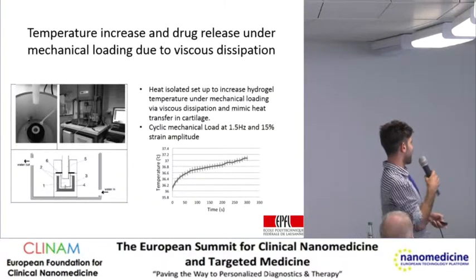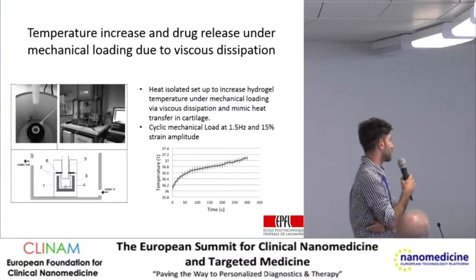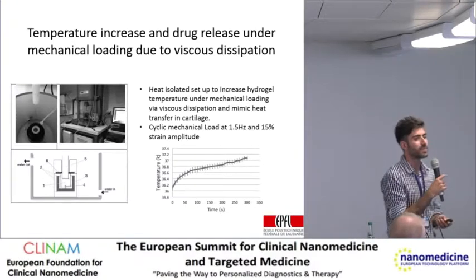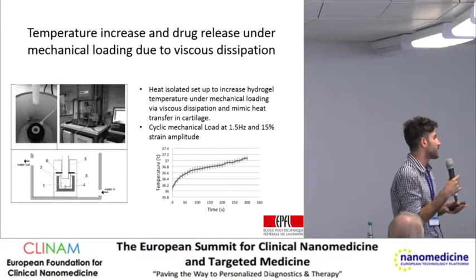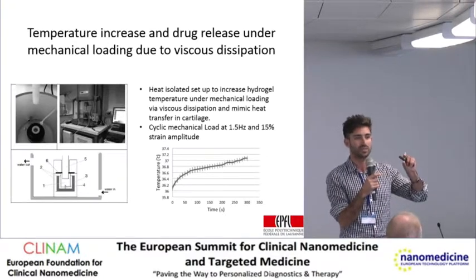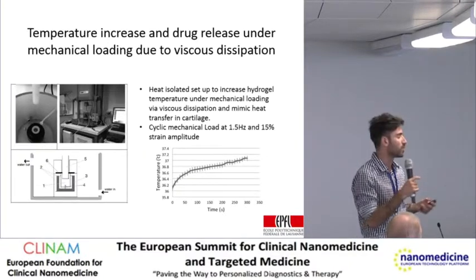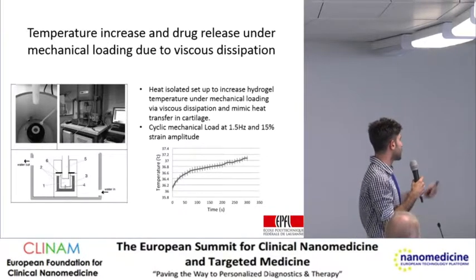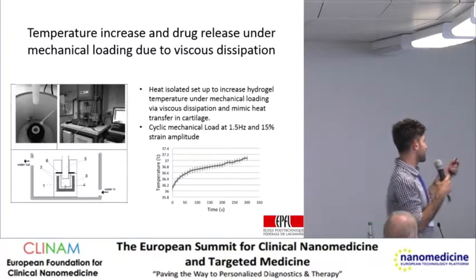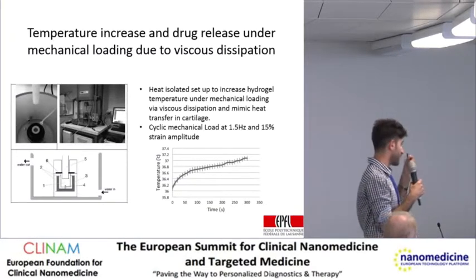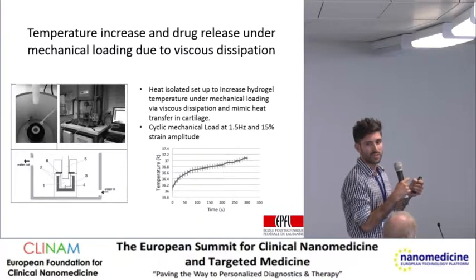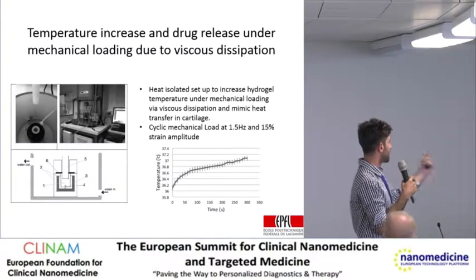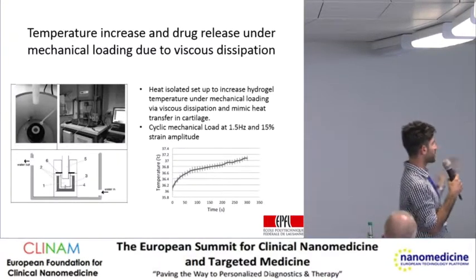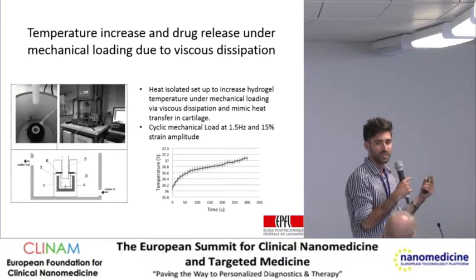Then we characterized drug release under load. For this, you need a system that is heat isolated, because we didn't want the temperature that we produce under load to go away, so we should preserve it somehow. So I designed a system with a two-layer wall with a vacuum in between, so that you can control the heat loss of the system, with a chamber around it with water perfusion, so that you can control the temperature of the environment.